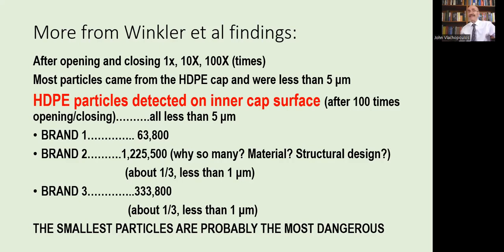Now, to make things even more interesting is the fact that the small particles are the most dangerous, right? So the opening and closing does result in release of microplastics, and as a matter of fact, release of microplastics that potentially are more dangerous to human health, which means that if we want to improve this product, we must really study carefully the most suitable material for the caps and also the most suitable injection molding conditions that would result in release of fewer microplastics during opening and closing.